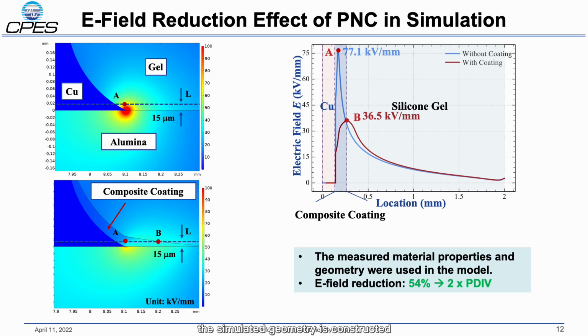The simulated geometry is constructed based on the optical observation we showed in the previous slide. So here's the copper, here's the gel, here's the alumina, and this thin layer is our composite coating. We use this measure line L to extract the E-field from the simulation. We can just look at this E-field distribution. We can see that after we apply the coating, the high field region, the red region, is significantly reduced.